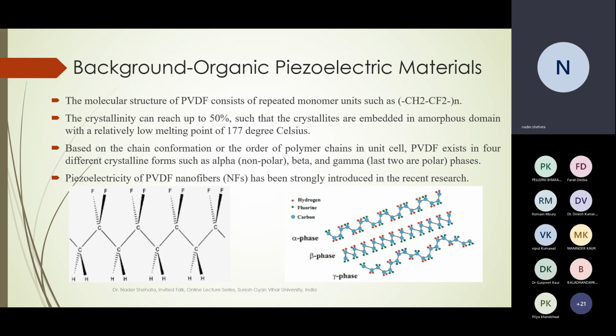So the molecular structure of the PVDF, as shown in this slide, consists of repeated monomer units CH2 and CF2, as shown in the left diagram. And the crystallinity of this organic material is quite good compared to different organic materials, because a lot of organic materials suffer from an amorphous nature. However, for this type of material, it could reach up to 50% crystalline structure compared to the surrounding amorphous domain of the material.